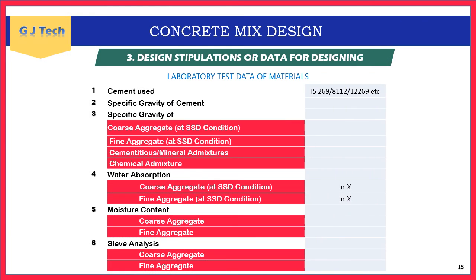After general information, test data required for mix designing includes: cement type complying to OPC grades 33, 43, or 53 per respective IS codes; specific gravity of cement, chemical admixtures, SCMs, fine aggregate, and coarse aggregate; water absorption for both aggregates; moisture content for coarse and fine aggregate; and sieve analysis values.